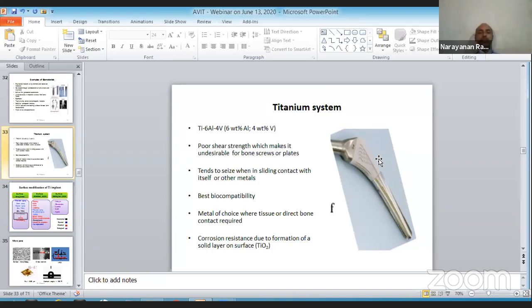Yes and no. Let us stick only to these implants. I told you there are major families: the stainless steel family, cobalt chromium family, titanium family, and magnesium family. Titanium is good. First of all, it acts as a support for the cells to form. Let us say I have a bone here, another bone here, which is broken. If I place the titanium metal, it acts as a scaffold upon which the cells can form. So titanium acts as a base material, just as a foundation for bone to form. Once the natural bone is formed, up to the level of acceptance by the orthopedic surgeons, it can be removed. It is not necessary that it has to be removed. So titanium can stay for a longer time, for 10 years, 20 years.